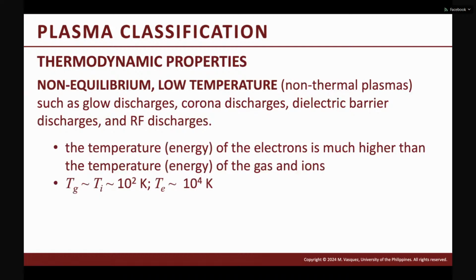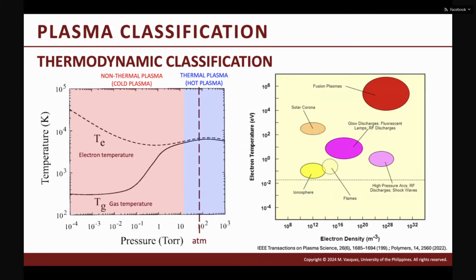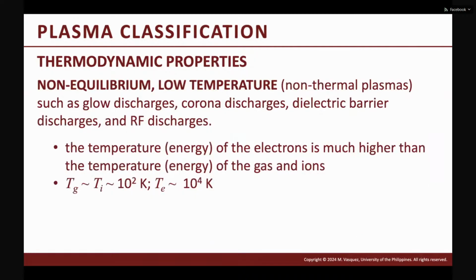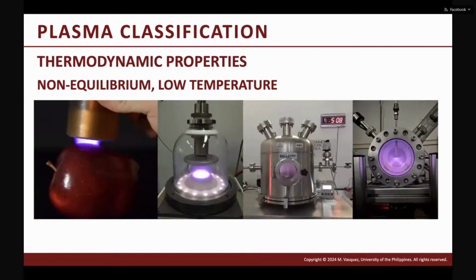So the first type is what we call the non-equilibrium or low temperature plasma, or non-thermal plasma, or sometimes also called cold plasma. This is typically in terms of glow discharges, corona, and even DBD. The gas temperature and ion temperature are usually near room temperature, while electron temperature is somewhere around 10 to the 4 Kelvin, or 1 eV. So these are examples of non-equilibrium low temperature plasma. This is heavily used in industry. It is used for thin film deposition, for surface modification, and so on.